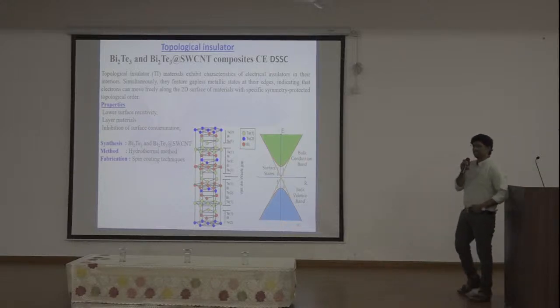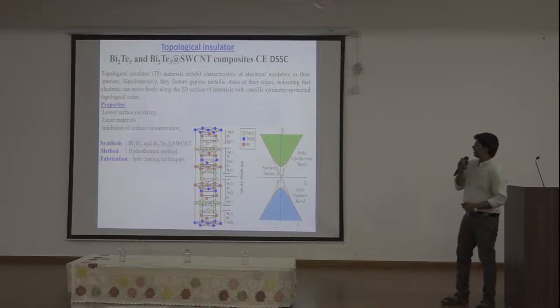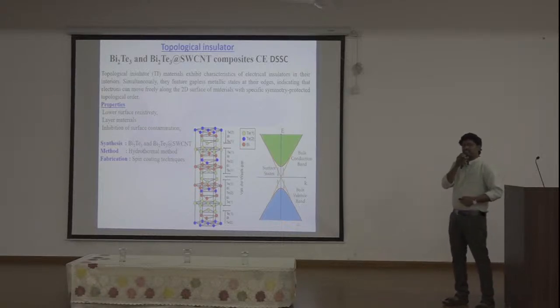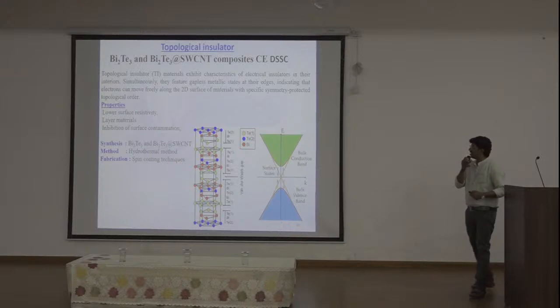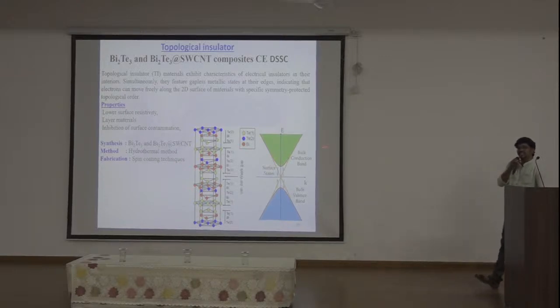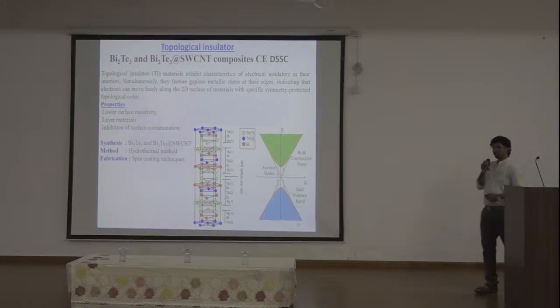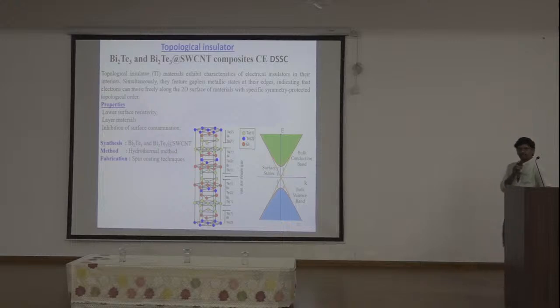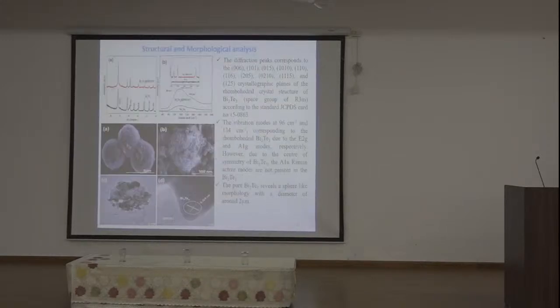and surface states behave. While this material is highly conducting in the surface state, it is insulating in the interior. So the electron can move freely on this 2D surface because of the high spin orbit coupling. That's why I became interested in this topological material, and in how it behaves in reducing the electrolyte in the counter electrode application.